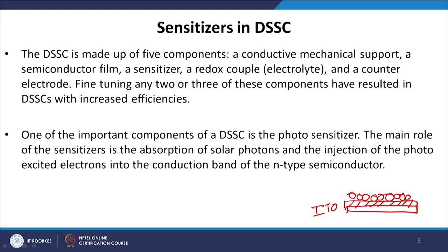Once adsorbed, the dye molecule is ready to absorb sunlight. The electron is excited from the ground state to the excited state of the dye, but the electron cannot stay in the excited state for long. So it injects into the conduction band of titanium dioxide. That is why energy level matching of the dye and TiO2 is very important — the excited state of the dye must be higher in energy than the conduction band of TiO2, so that the dye in its excited state can inject electrons into TiO2's conduction band.